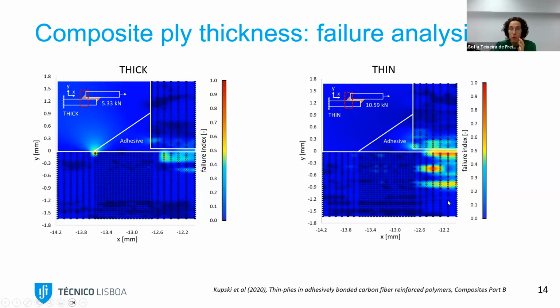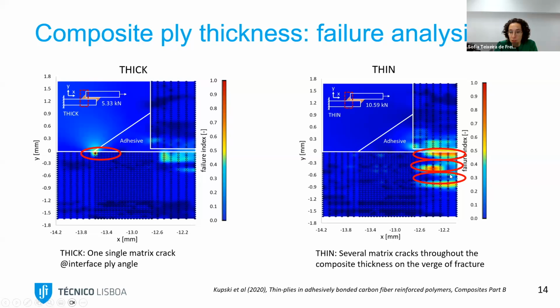So what does it tell you? When we compare with the fracture surface that we had, how does this match? Well, I think it matches pretty well, because for the thick, we have one single matrix crack at the interface ply angle, which matches pretty well with the one flat fracture surface for the thick that we've seen in the profilometer. And for the thin, we see several matrix cracks throughout the composite thickness on the verge of fracture. So what it means is that when we decrease the ply thickness, we create more regions where the material is being used and is getting closer to failure.